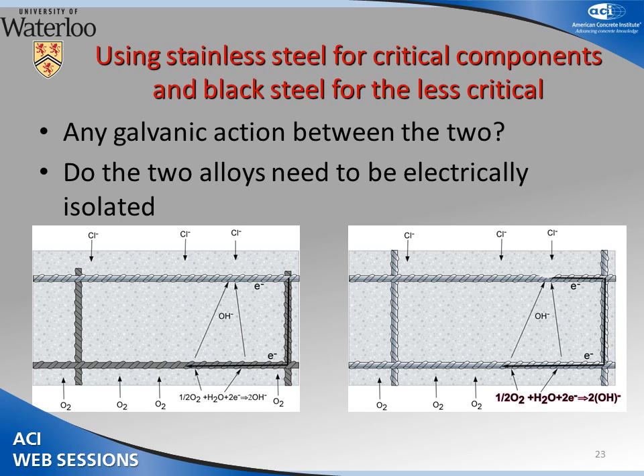And until this work, the authorities throughout North America were electrically insulating the joints between the black steel and the stainless steel. And that, of course, is very costly, both in time and money. And what he found was this reaction, which I've highlighted here, it's the same one as here. This should have been all in black, by the way. This reaction, which is the cathodic reaction, the reduction of oxygen, which drives the corrosion rate.